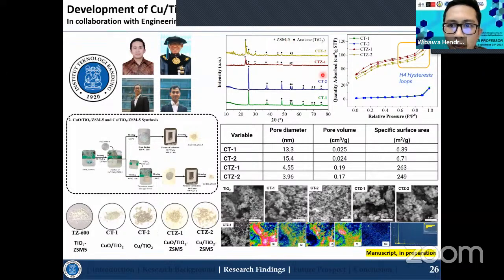So the XRD patterns and also the BET. We can see that by using a zeolite as support in these cases, the specific surface area is significantly improved compared with only using the TiO2. It's almost around 40 times compared with the copper that is doped on TiO2. And from the EDX measurements, it can also be confirmed that the copper is homogeneously dispersed into the zeolite and also the TiO2 itself.